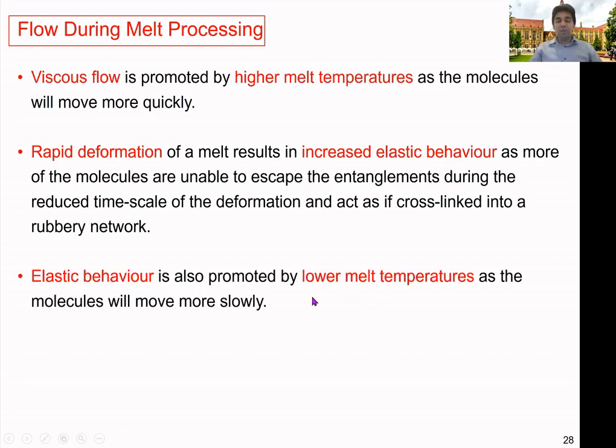Elastic behavior is also promoted by lower melt temperatures, as the molecules will move more slowly. Lower screw speed and lower set temperature of the barrel will provide a lower melt temperature, meaning higher viscosity — so the behavior would be more elastic. We should choose the set temperatures not to create any issues, but to get the required output rate, thermal quality, and so on. It is really important to find the best possible settings for a given machine, material, and screw.